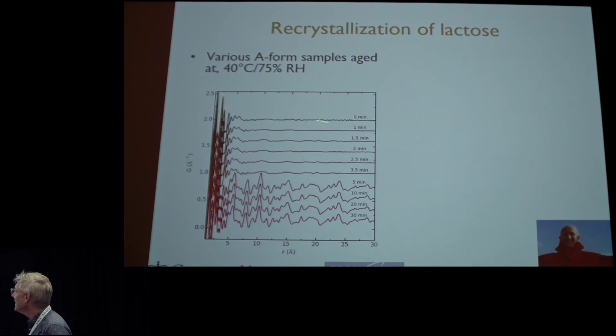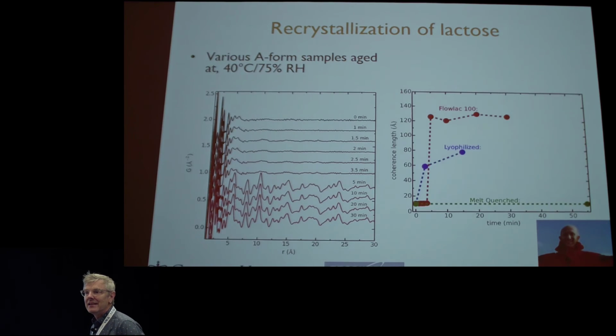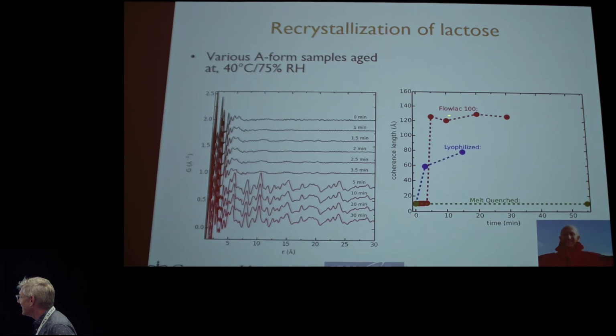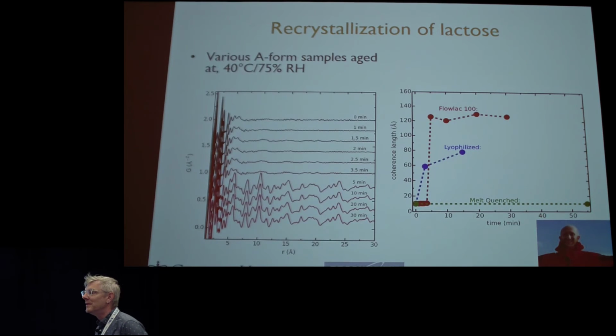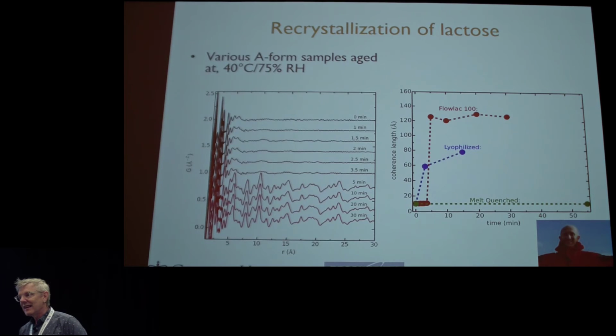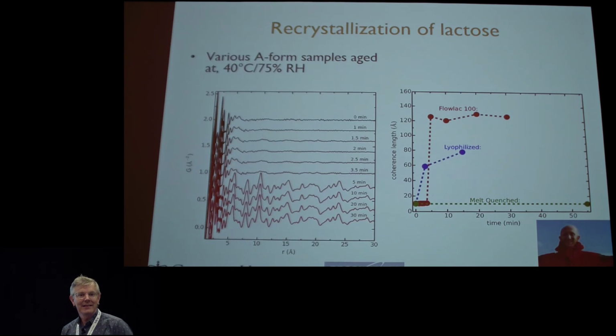And so what we wanted to do is actually study what this pre-crystallization product is. We can look at the kinetics is one thing we can look at. So the amorphous material made different ways. This is the commercial one. This one lyophilized is freeze-dried if you're not a pharma person in the audience. And we had a melt quench one which actually never recrystallized. So this is a very stable amorphous form. We actually think that the presence of water in the material is like a lubricant for the recrystallization.